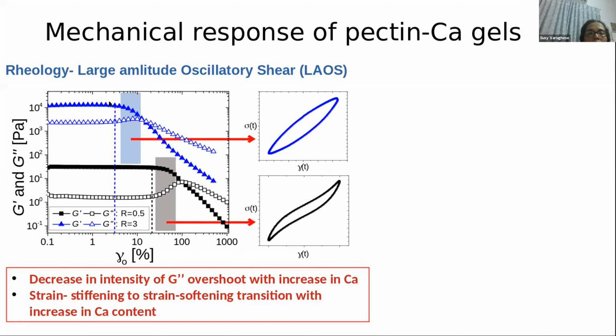One is known as the storage modulus, which shows the stiffness of the material. You can see that in the blue, which is R equal to 3, when the calcium is high and when calcium is low, this material shows entirely different behaviors. The empty symbols here, the black one is for low calcium, and the blue one is for high calcium. G double prime indicates how much the material is fluid-like, and G prime, the solid lines, indicates how much of the material is solid-like.